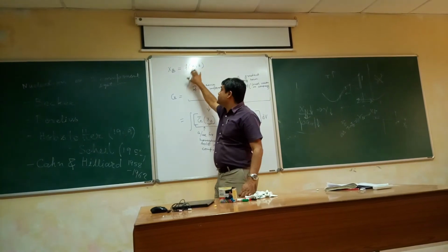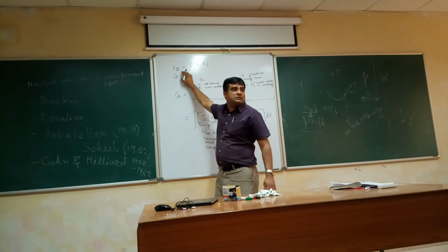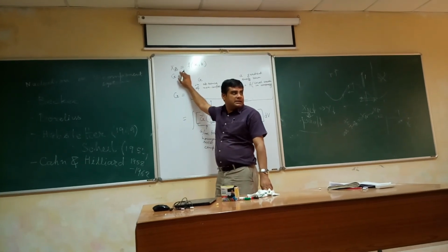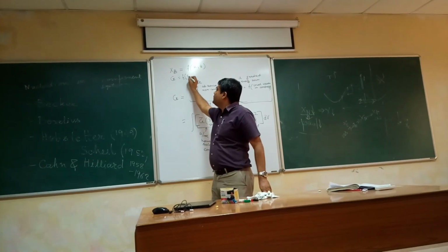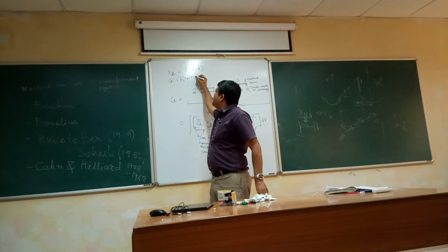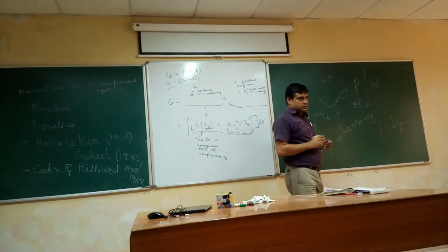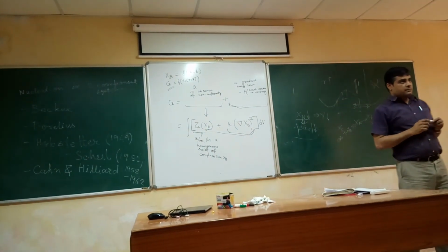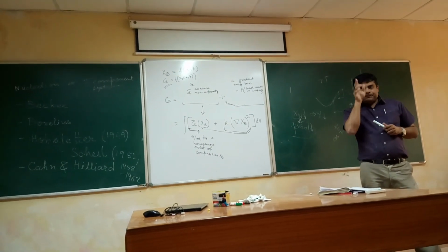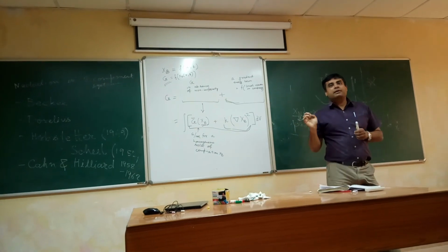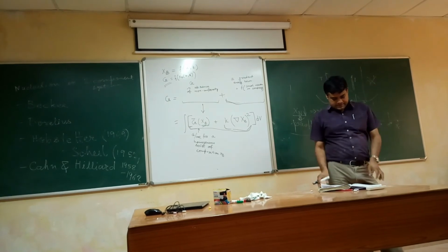So xb is not a scalar quantity, and Gibbs free energy is a function of xb, which is a function of space and time. That means Gibbs free energy is a functional. With this Gibbs free energy, the saddle point will give you the nucleation, delta G star.